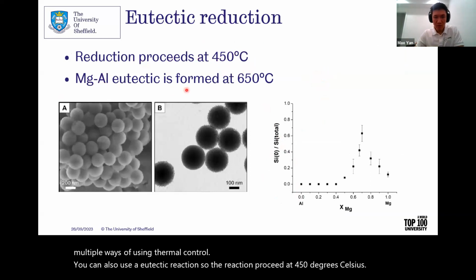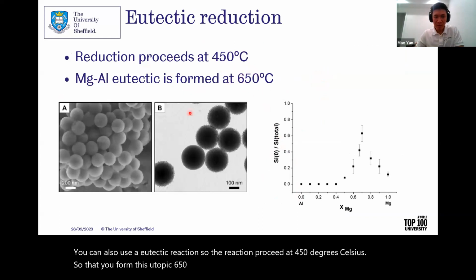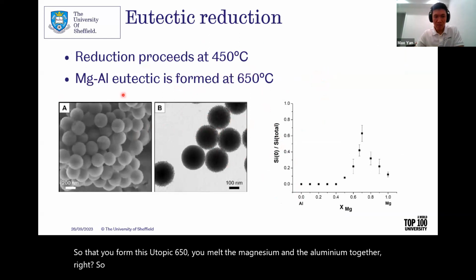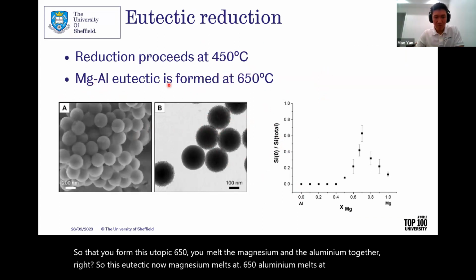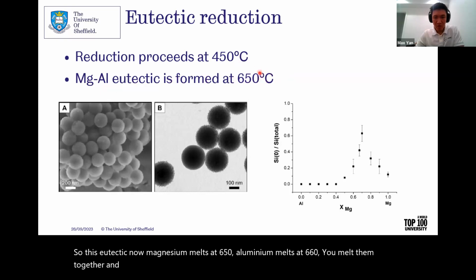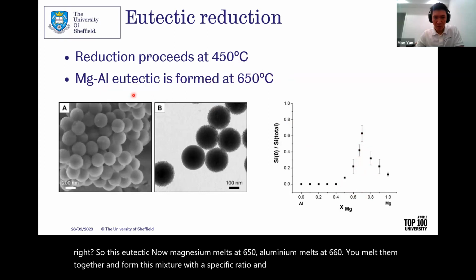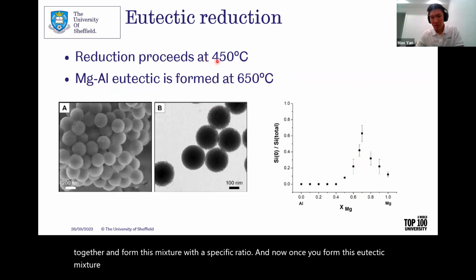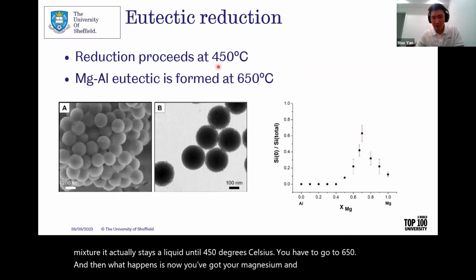So you form this eutectic at 650, you melt the magnesium and the aluminium together, right? So this eutectic now, magnesium melts at 650, aluminium melts at 660. You melt them together and form this mixture with a specific ratio. And now once you form this eutectic mixture, it actually stays a liquid until 450 degrees Celsius. You don't have to go to 650. And then what happens is now you've got your magnesium in the liquid phase at 450.